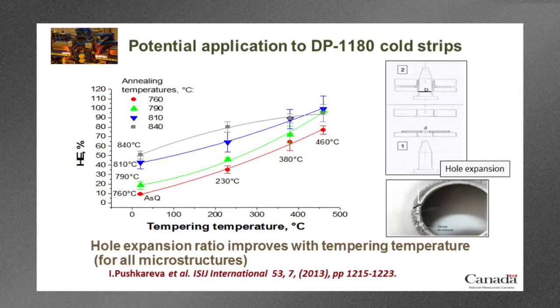Then from that we can calculate the ratio, the difference between the two diameters, divided by the original hole diameter, and we get this hole expansion coefficient. So the more ductile the material, the more damage resistant the material, I should say, the higher will be the value of the hole expansion coefficient.